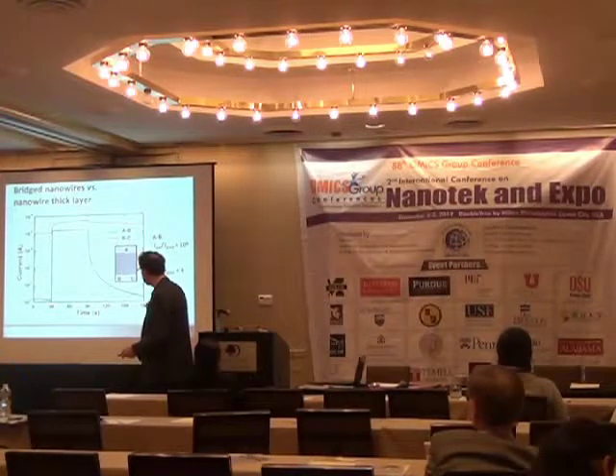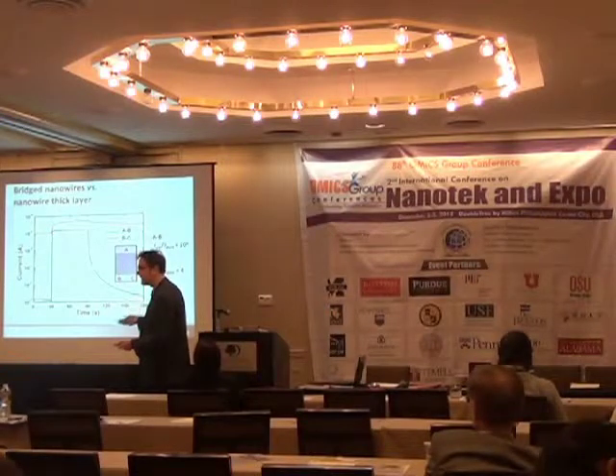This is a photoconductor. Between the points B and C, what you have is a thick layer, so you measure the characteristics of the thick layer, in red here. It doesn't respond well to UV. You start with a very large dark current, and you have a low response. So this is not very exciting. This is just the response of a thick layer of zinc oxide throughout the plane.